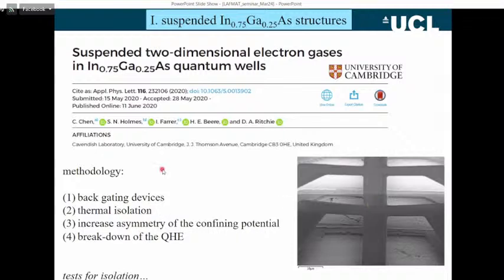And what we did in this work was to demonstrate a thermal isolation. And what happens is when you apply a current to these suspended layers, because there's nowhere for the heat to dissipate, the electron temperature rises very rapidly, and we can measure that. We can measure that electrically. So in this paper that was published in Applied Physics Letters, we demonstrated very clearly that these suspended layers were thermally isolated.